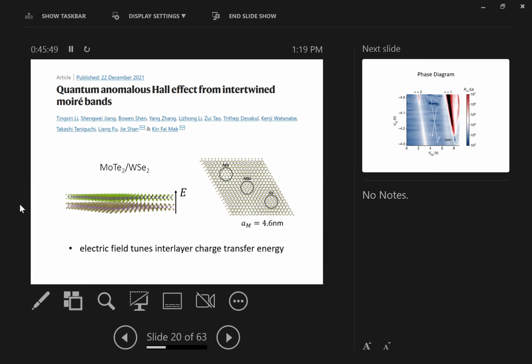And in this system, the Moiré superlattice period is actually smaller. It's 4.6 nanometers. So quantum mechanical processes are more important. These are much further away from the extremely correlated limit. So that's where things get more interesting. So I just want to say here, the role of the electric field is actually to tune the charge transfer energy. And now it's between the 2 layers. Okay, in this system, we can transfer charge not just between different regions of one layer, but actually between the 2 layers.